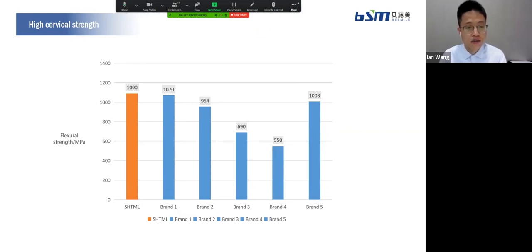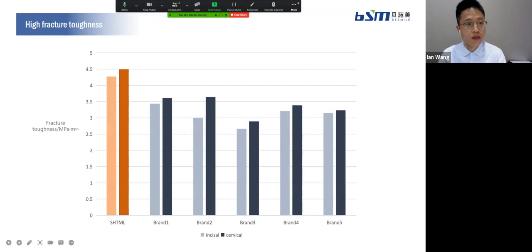So with the high cervical strength, it can ensure the whole strength of the restoration. And as a result, it can ensure the long service life of the restoration. And at the same time, we also test the fracture toughness of incisal part and cervical part. And we can see no matter for the incisal part or cervical part, our SHTML has an obviously higher fracture toughness than other 5 brands. So with the higher fracture toughness, the restoration can have a higher ability to resist the micro crack, and also it can ensure the service life of the restoration. So it proves our SHTML has a higher stability.